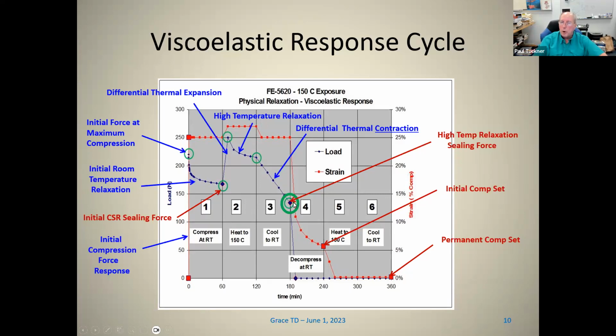And then if, at this point, you take it out of the jig and allow it to sit for 30 minutes or 60 minutes, the specimen should recover a certain amount to what it was originally. That's what I would call the initial compression set, or the room temperature compression set value.